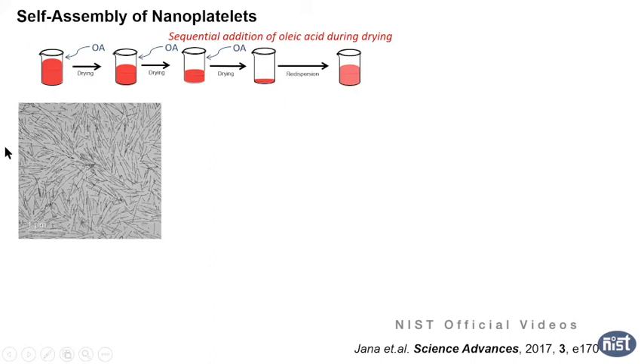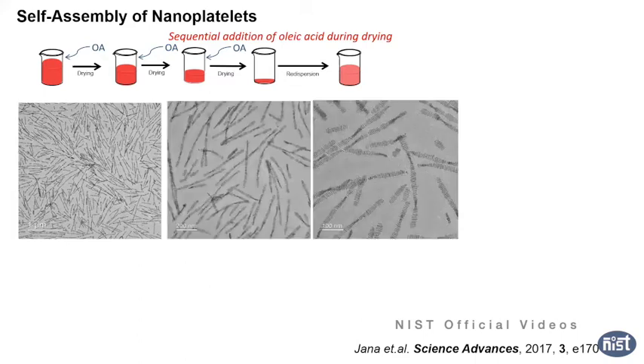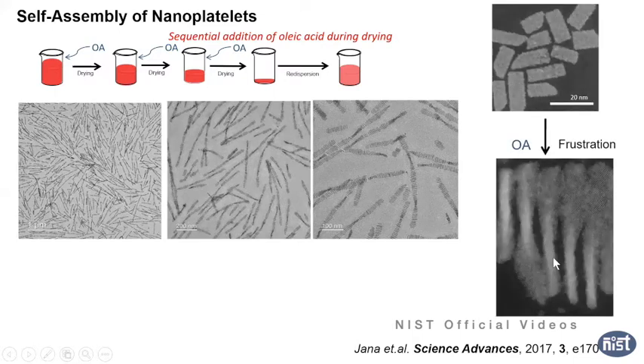These are like a rod or thread, you can say, but it's not one crystal. It's attached with all platelets together. If you zoom to a high magnification image, you can see these are platelets stacked along the direction. And the interesting thing is that when it goes to this kind of structure, your nanocrystal has a